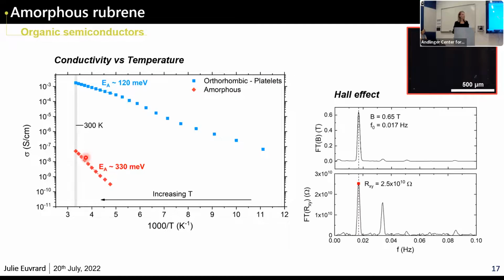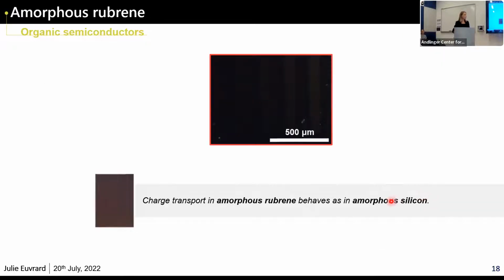Now, what about Hall effect? Well, actually, we do have a peak here. So we do have a Hall signal. It's not pure hopping, but when we extract the data out of it, we obtain a density that is 5 orders of magnitude lower than what we should expect. And this is because this technique is only sensitive to the band-like carriers, but does not see the hopping carriers. And the vast majority of carriers here are hopping. So this film is not purely hopping, but mostly hopping, which is also what we observe in amorphous rubrene, especially when we go down in temperature.